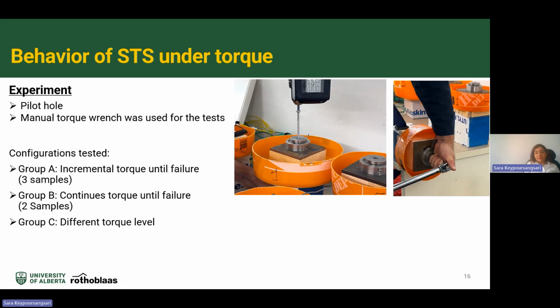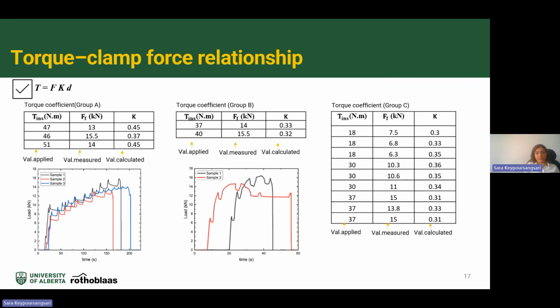So in this part, I mean in dry condition in step 1, first we made a pilot hole and then we installed the self-tapping screws. When the head of a screw reached the steel plate, we used the manual torque wrench to tighten the screws. We divided our samples into 3 different groups. In group A, we increased the torque incrementally. In group B, we increased the torque continuously. And in group C, we increased the torque to different levels. In groups A and B, we increased the torque until we got a failure. But in group C, we just increased the torque before getting any failure. So in group C, we don't have any failure.